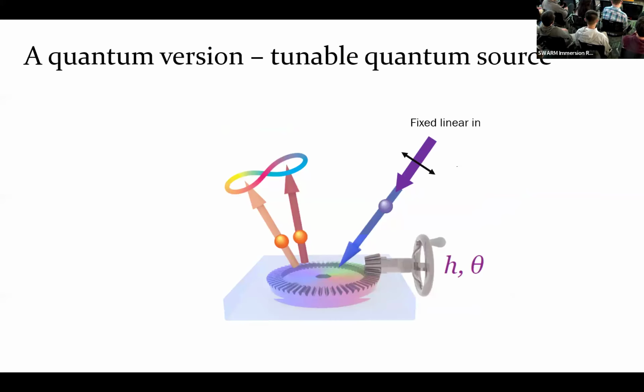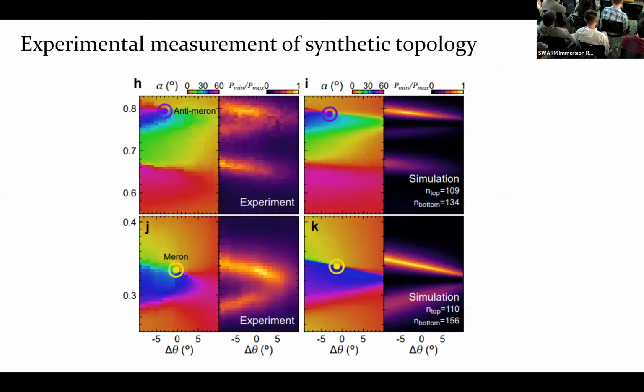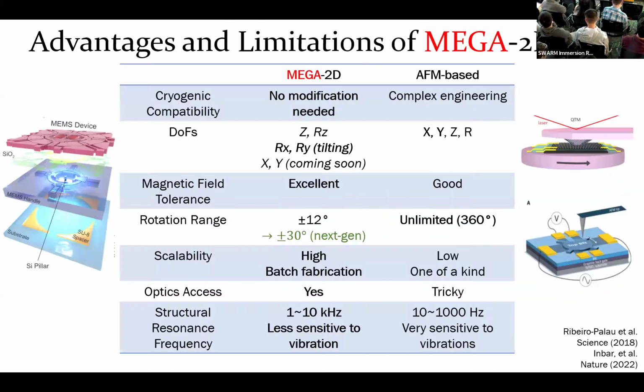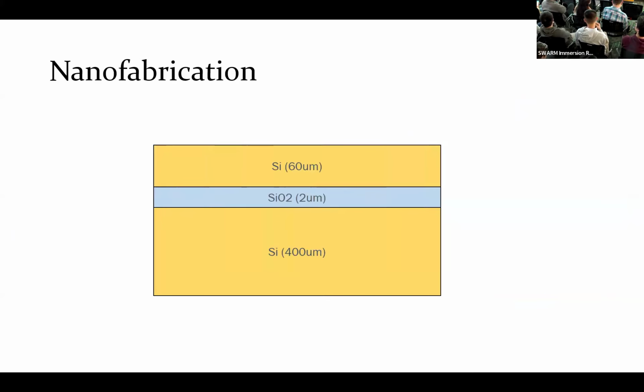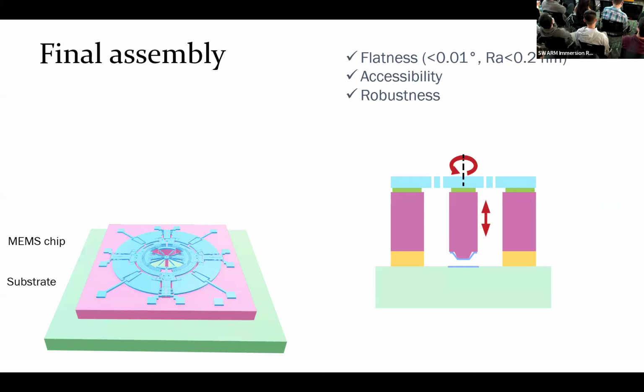So SU8, if spin coated, is supposed to be flat within maybe tens of nanometers at least, right? The device is about 6 millimeters in dimension. So if you're just tilting it by tens of nanometers, it's basically not tilting that much. That's within the flatness requirement that we have. We're saying the flatness requirement is 0.01 degrees, so that's definitely within that range.